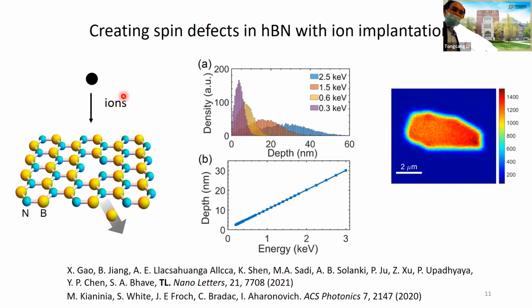So then we want to create a spin defect in hBN with ion implantation. We built a small ion implanter, and it turned out helium ion is the best to create this defect. And we did some calculation. The depth depends on energy. For example, with 300 eV, the average depth will be about 3 nanometers. If you increase the energy to 3 keV, then the average depth will be about 30 nanometers. With that, we can create a homogeneous spin defect across the surface. The depth can be controlled by the energy, or we can peel it off later to reduce the depth.